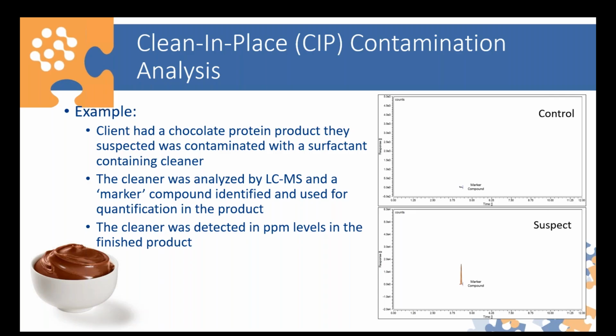From there, we developed an LC-MS method to look for lower levels of this particular marker, and by proxy, the cleaner in question. Unfortunately, in this case, we did detect the cleaner in the suspect finished product in ppm levels. And so they did have an incident they needed to address.